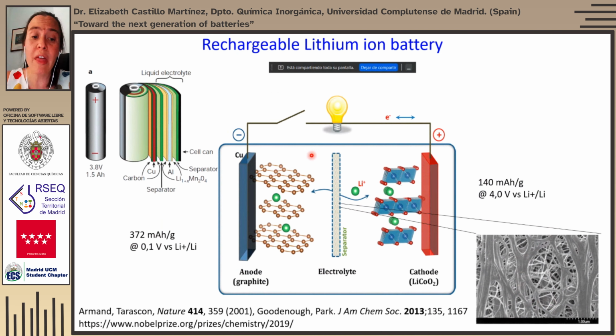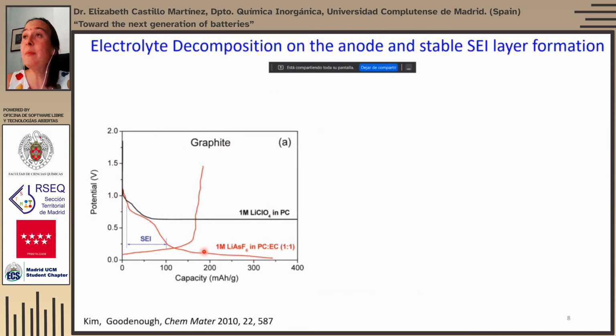As you can see, both the anode material and the cathode material have a layer structure, and they have capacities of about 370 milliamp hour per gram and 140 milliamp hour per gram. You don't need to remember these numbers, of course, but this is to give you an idea, as I will be talking to you about other values for other materials that have been developed. And what is important is that the voltage difference at which the redox reaction takes place on both the cathode and the anode is quite large, about 4 volts approximately. But the development of these batteries had other issues to be solved.